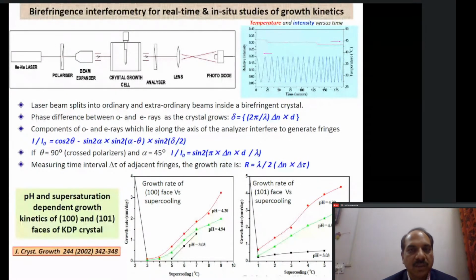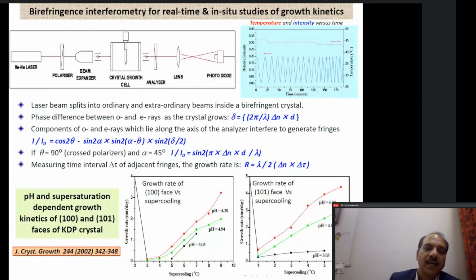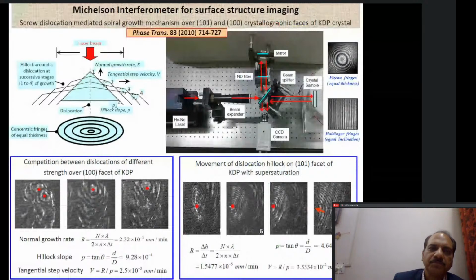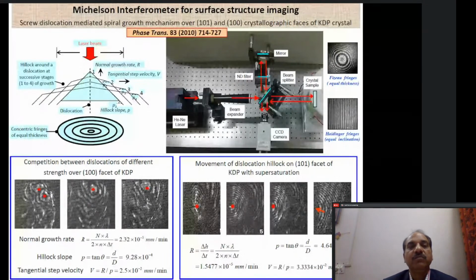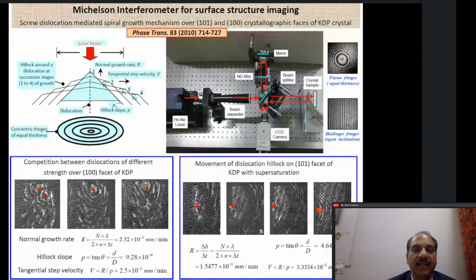And we have been able to use this technique to find the effect of temperature as well as pH on the KDP crystal growth morphology, and we published it long back. So this is a technique which we now very regularly use on many different crystals. This is a Michelson interferometer which we have set up, which we use for basically finding out what is the growth mechanism, especially if the growth mechanism is a screw dislocation mediated growth mechanism, then we can find that out using this Michelson interferometry.